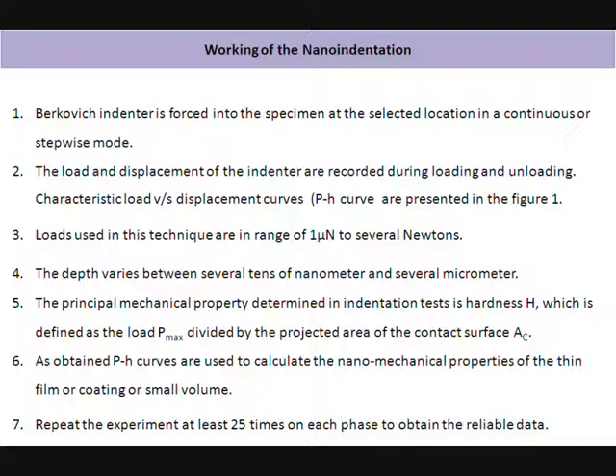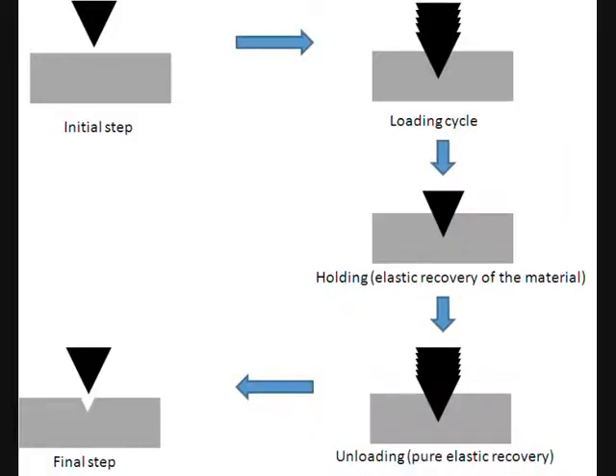The working of the nano indentation is as follows. First, a Berkovich indenter is forced into the specimen at the selected location in a continuous or stepwise mode. The load and displacement of the indenter are recorded during loading and unloading. A schematic of the whole experiment is presented in this slide. The indenter is pressed against the material. After attaining the maximum load, the indenter is held at this load for 2 to 3 seconds, so that the material can recover and we can avoid thermal drift and inertia.